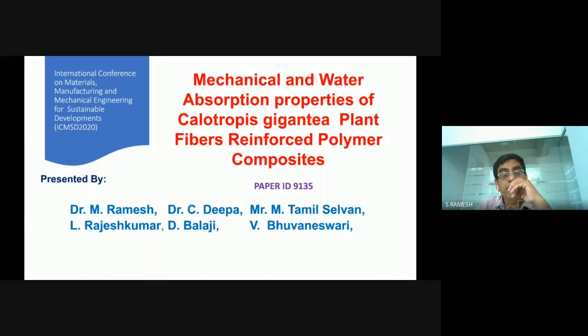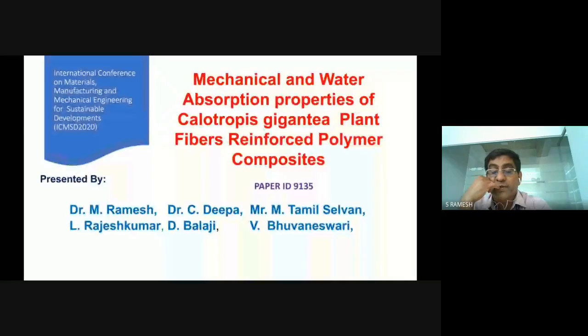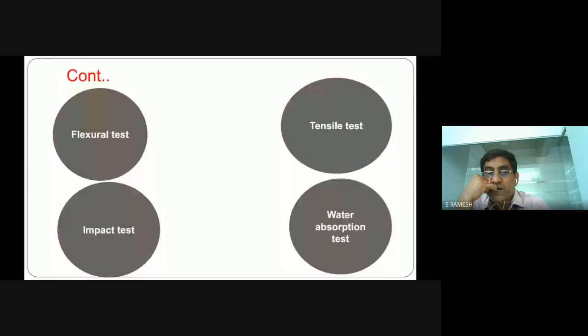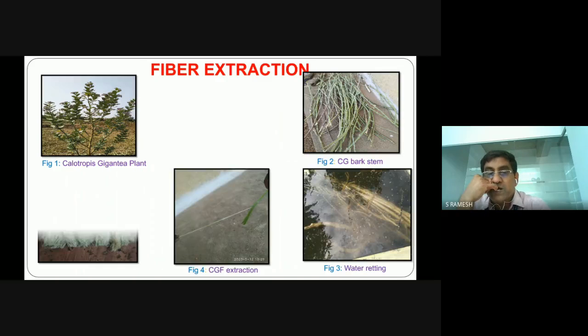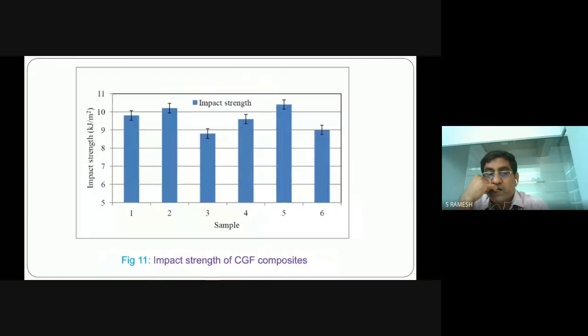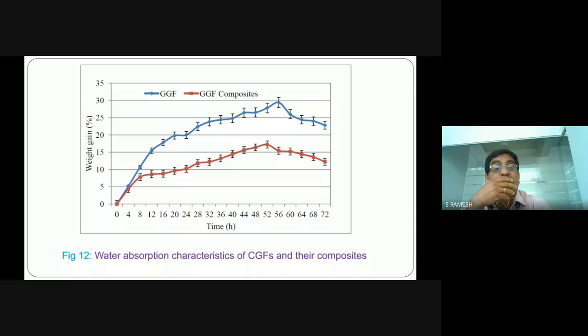Yes, sir. In the water absorption test, we use the water absorption tester machine. We take 72 hours as the total time, and we record it every 4 hours. I will explain from the graph in a detailed manner. Normally, we take the weight gain as a percentage. Weight gain percentage equals wet weight minus initial dry weight, divided by initial dry weight, into 100. This is the formula.